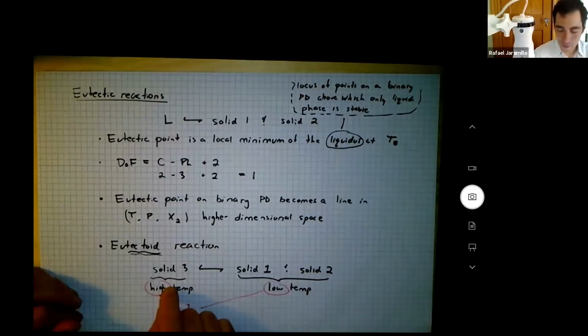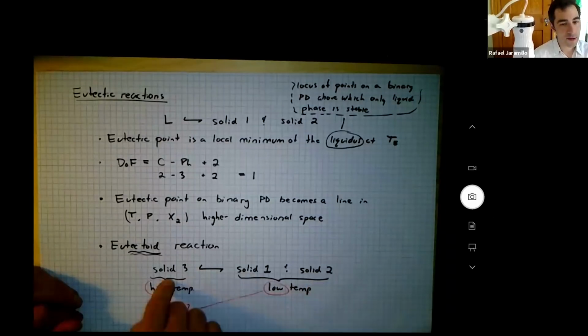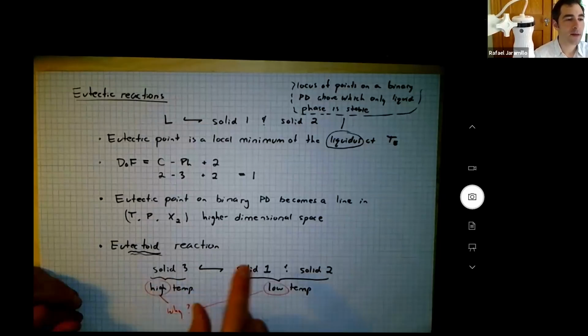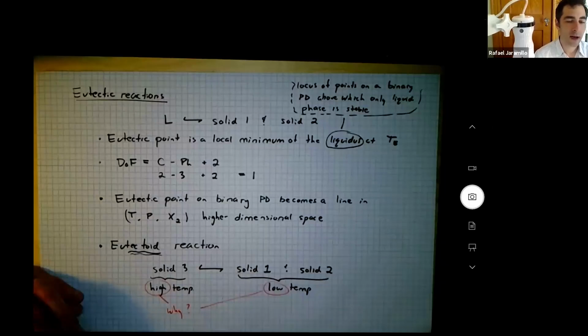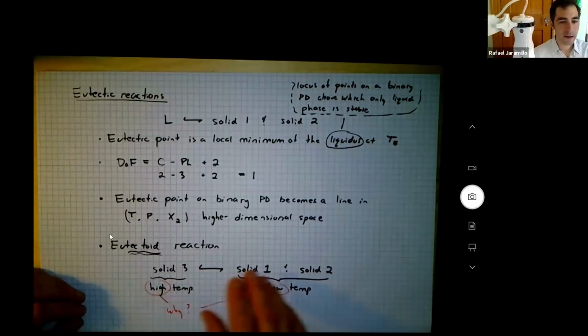If you have two solid solutions and you take all those components and mix them into one solid solution, you necessarily have a higher entropy of mixing in this case than this case. You can convince yourself of that by drawing your own free energy composition diagrams. So in general, high entropy things are favored at higher temperature, right? This is something that you know.